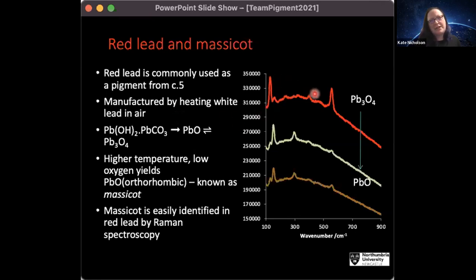So the red lead that we produce, the minium, is the spectra shown on top here in red. If you slightly over roasted or under roasted your red lead, you would get a massicot or a litharge. And we can see that the peaks shift into different positions with the chemical changes in the pigment. Now, massicot contamination in red lead is easily identified in Raman spectroscopy. The red lead that we see in the 7th and 8th century Northumbrian manuscripts is pristine. They were outstanding chemists.